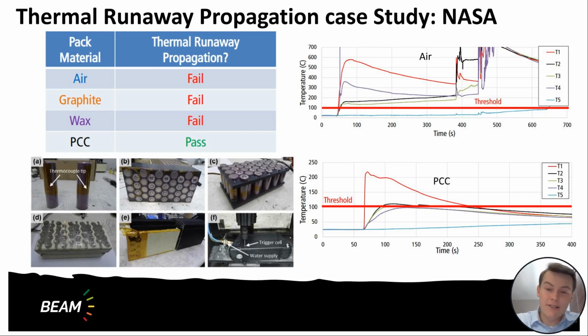Compared to the air test, obviously you get the initial spike in temperature due to the induced failure in the purple curve at around about 50 seconds. And then within seconds, you get propagation of neighboring cells, and propagation continues throughout the whole pack over several minutes.